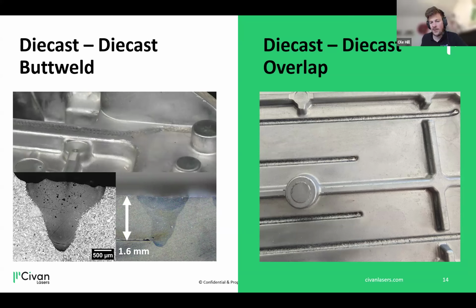On the right-hand side, you see the same part, but in the middle it had a few sections of overlap. There we use a different kind of beam shape, one that has a more centered energy to go deeper inside the underlying material. We didn't need a wide weld seam. On the left side for the butt weld, we intentionally go a bit wider to cover up any gaps that might appear. But for overlap, you don't need to cover gaps in the X direction, more covering gaps in the Z direction. And what you see is the cover image of an overlap of a die-cast cover into a die-cast chassis.